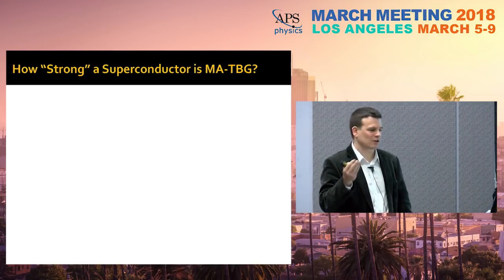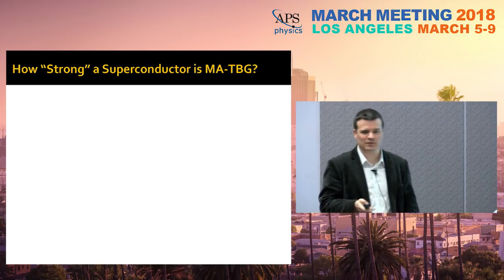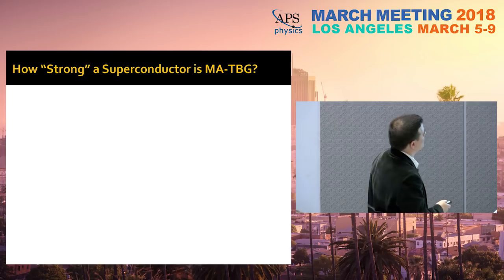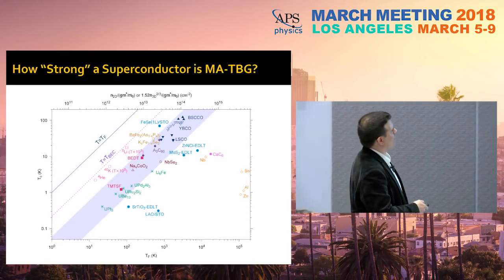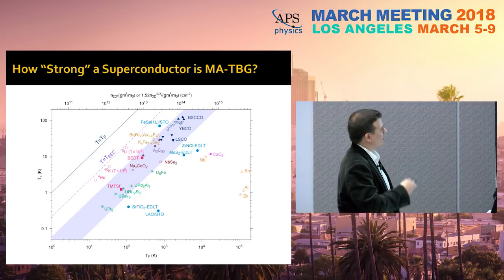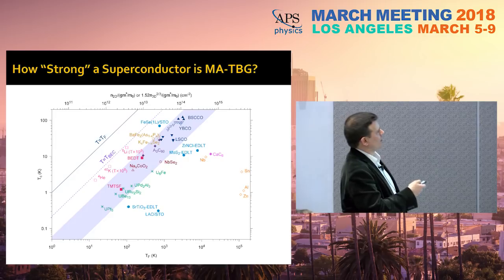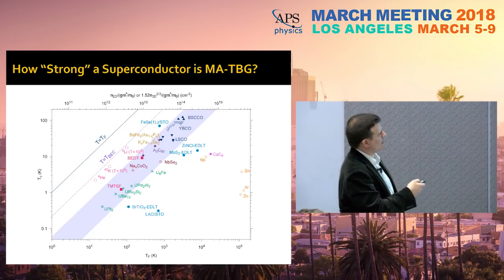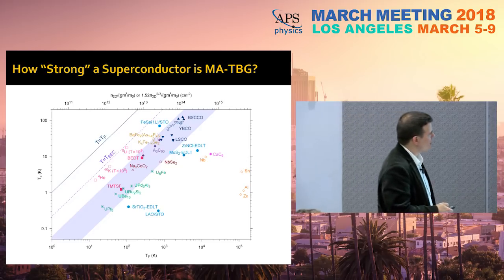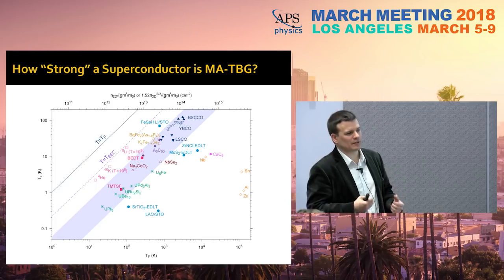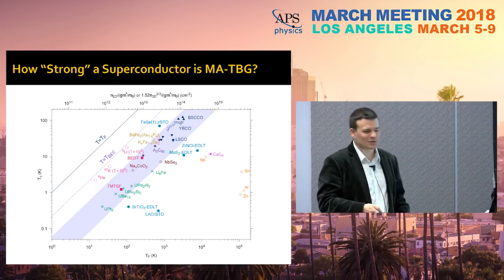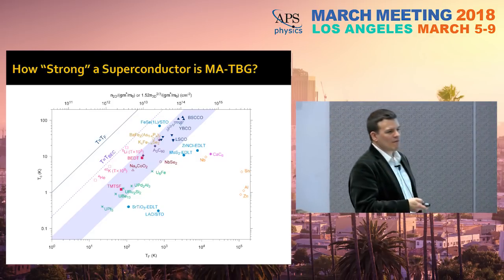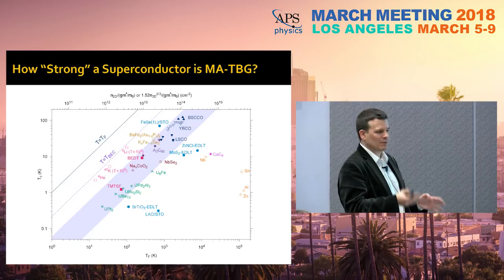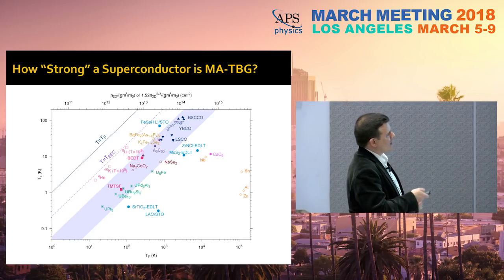But usually the way to compare superconductors, what makes a superconductor very strong, is not just the absolute value of the critical temperature, but how strongly it is superconducting given how many electrons you have in your system to superconduct, okay? So this is typically represented in this type of plot, which is in log-log scale. You have a critical temperature and Fermi temperature or density, and density you can convert for 2D or 3D. We're making them here 3D objects, we're converting them to 2D, okay? And this is telling you about how strongly coupled your superconductivity is. And this plot has been shown by one of the previous speakers with extra data points that I was glad to see. Conventional superconductors, which are explained by weak coupling BCS theory, are typically in this corner here.